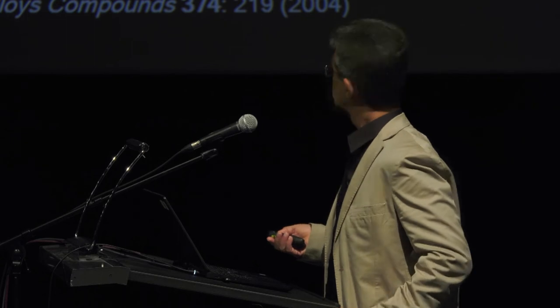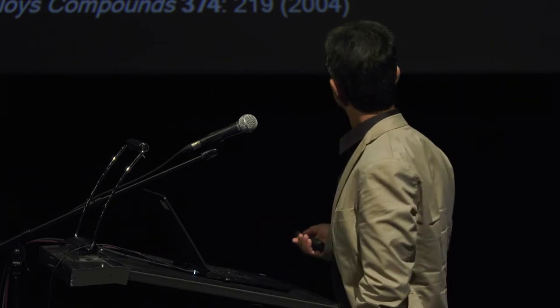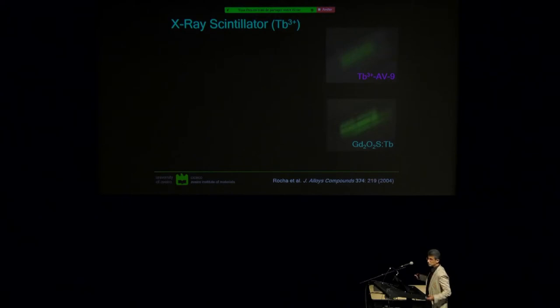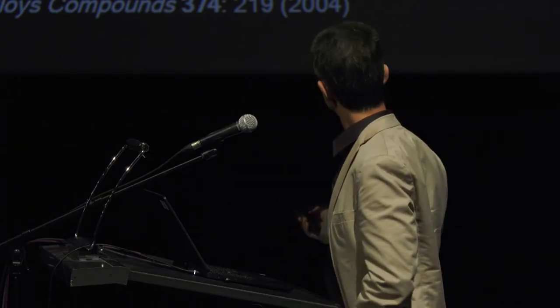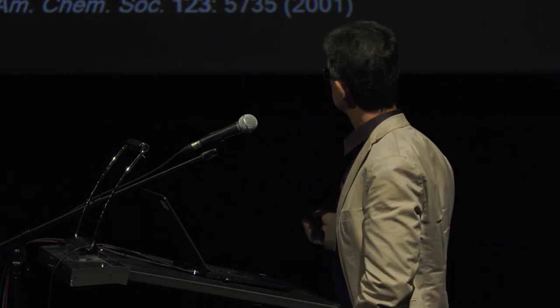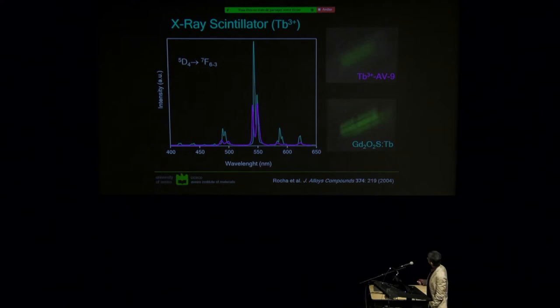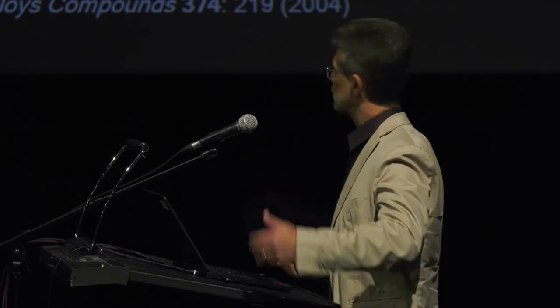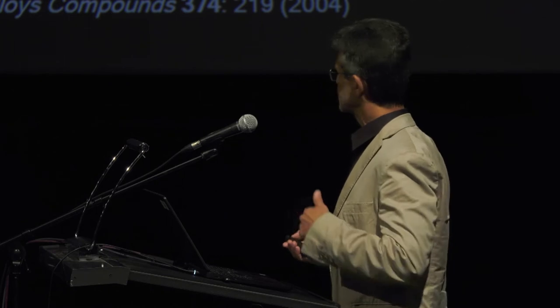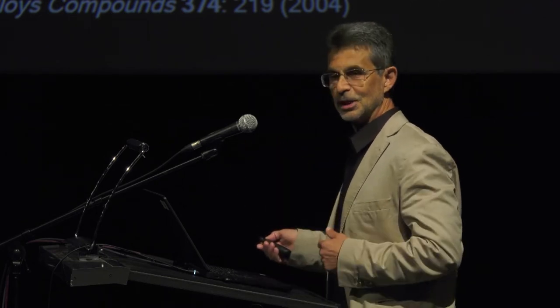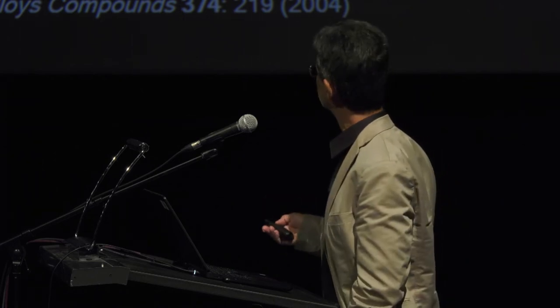So we took the sample to our X-ray diffractometer, and this is what we saw. It was returning green light. And this was comparable to the material we were using to align our X-ray beams, provided by Philips at the time. Then we just took a spectrometer to the XRD machine, and just measured the spectra, and that's what you get. And we compared, by integrating the areas, we could see that our material has about 60 to 70% of the emission of the Philips material, but our material is extremely light. So in a conference, there was a guy from military applications who came to me because he thought this could be interesting, I don't know for what purpose.